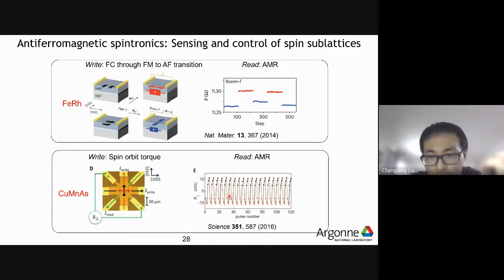So you see, in both of these cases, people are using an AMR effect, which uses a current to measure the resistance. And in particular, for this case, people may need to use a very high current to induce strong spin current to tune the Néel axis. That could be very, very power hungry and not good for low power application.